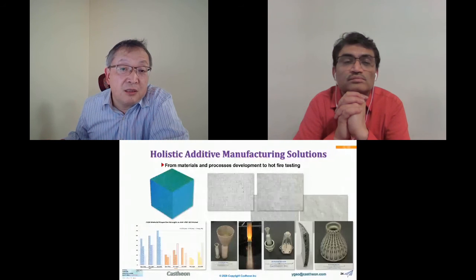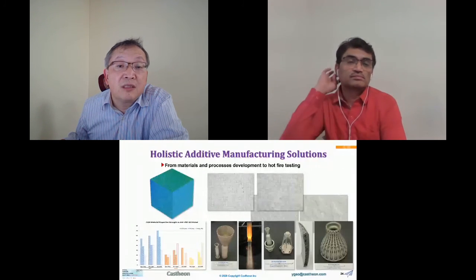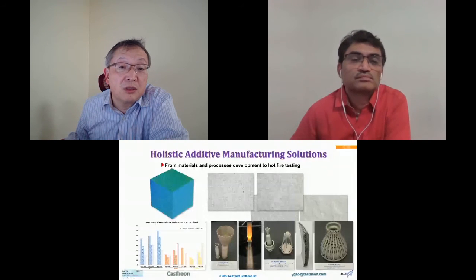And on the right, this material has been exposed to 2,900 degrees Fahrenheit for 2 hours. So what we're seeing is this is an extremely stable material.